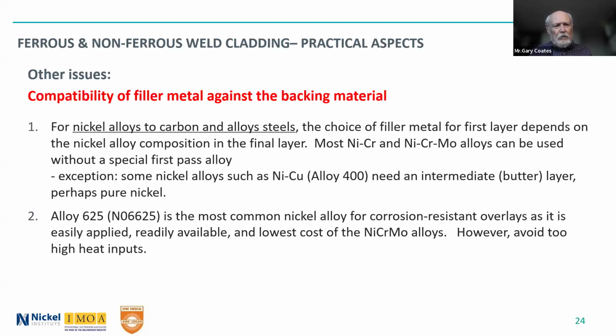And the other thing about 625: let's say the customer wanted a 6% moly overlay. Well, there is no matching filler metal for the 6 moly alloys, the 254 SMO, AL6XN type materials. They are welded with 625 or one of the C alloys, but you can use 625 to get the same corrosion resistance there. So 625 is commonly used even when you don't need the 625 corrosion resistance.